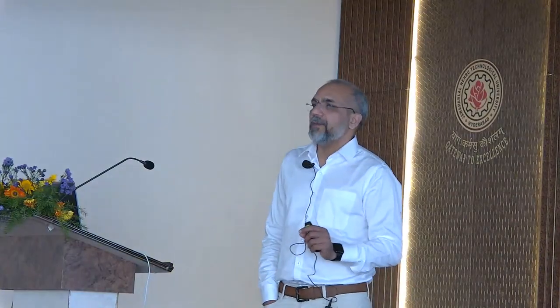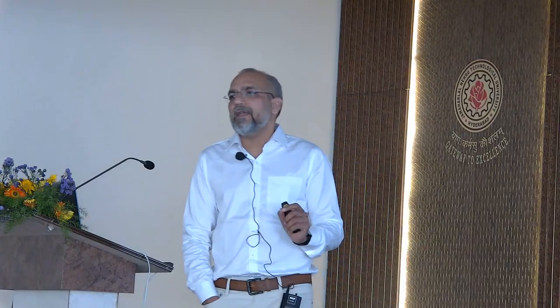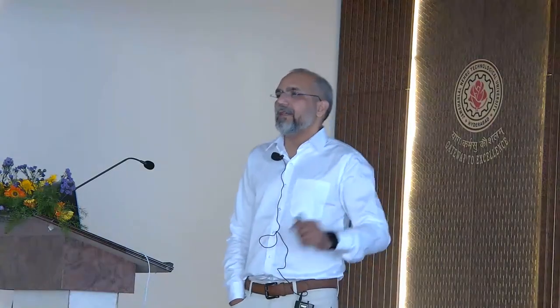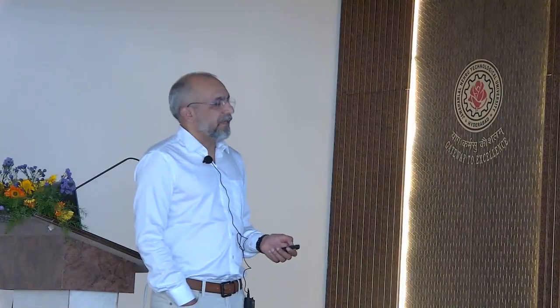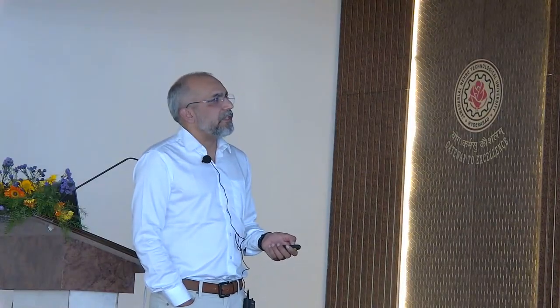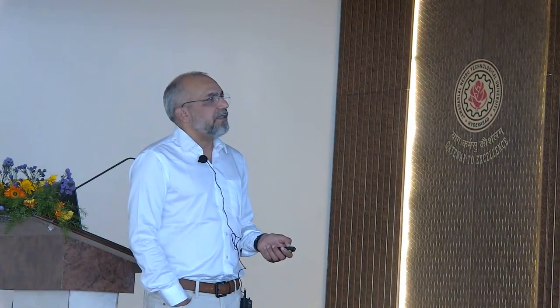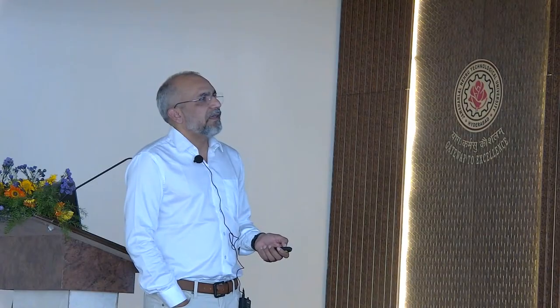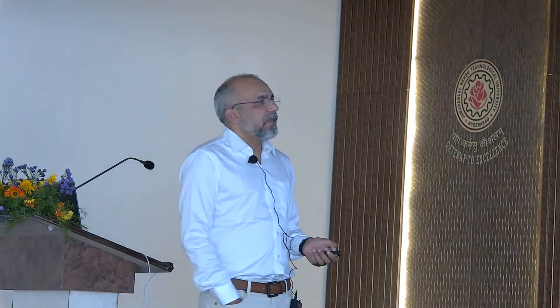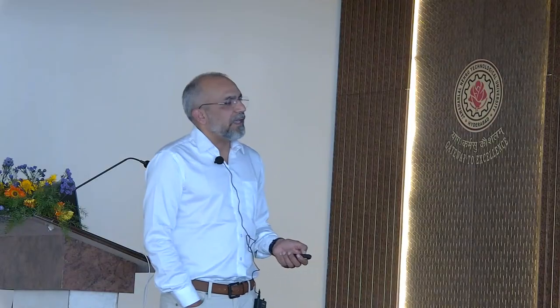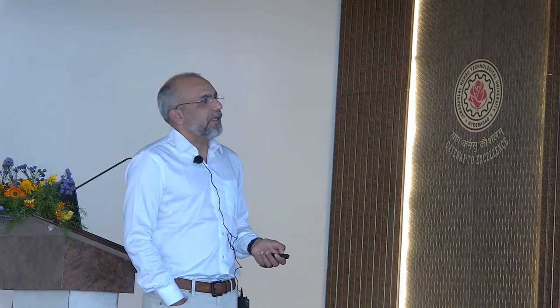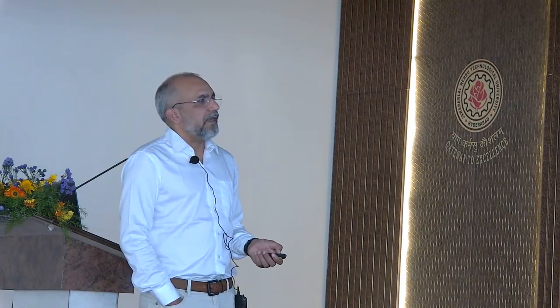So that was about the top-down approaches, and the best is mechanical exfoliation, from the recently published article. The second is chemical vapor deposition. Again, it looks like a very simple technique. It has 3 steps: first is precursor injection, then the reaction site, and then the gas ejection module. So 3 sections here. For example, to grow graphene, you have methane, hydrogen, and argon.